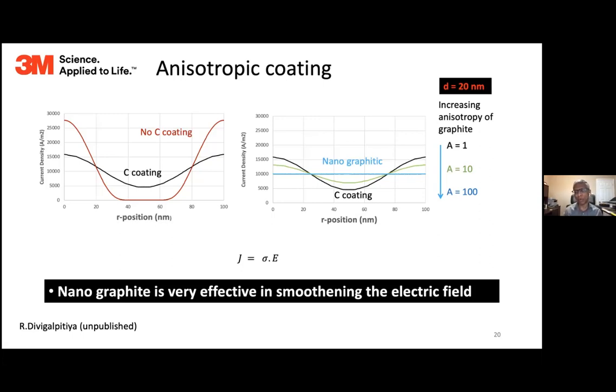As I said before, graphene or graphitic materials have much higher anisotropy. It conducts way better in the XY direction. So what this does is it evens out the current density right across the interface. If you look at Ohm's law, the current density is proportional to the electric field. So what this shows is that these graphitic coatings are very effective field spreaders. That's really the physics behind why it's working so well, which prevents the corrosion. It limits the potential to that small area that doesn't allow it to corrode.